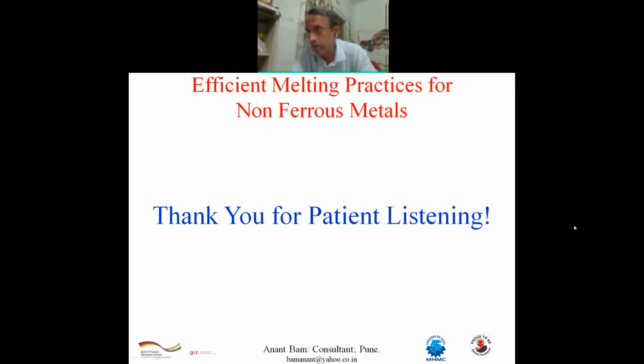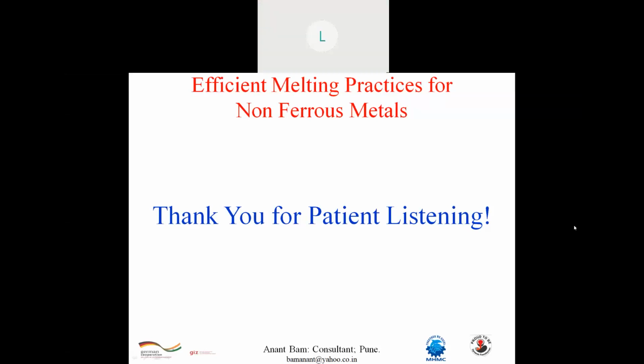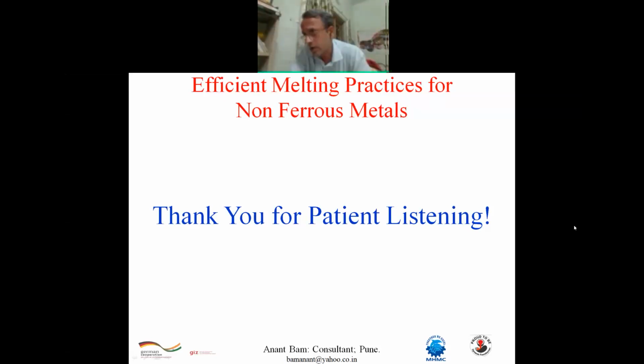So, we are doing that. And we are doing argon purging also. Then what is the purity of argon? Pure argon, sir, 99.9%. Okay, 99.9 will not suffice. 99.997 you require, with 0.03% maximum moisture. That is UHP, ultra high purity argon. Even nitrogen will do. Whatever you get, either argon or nitrogen, but you have to go for ultra high purity.